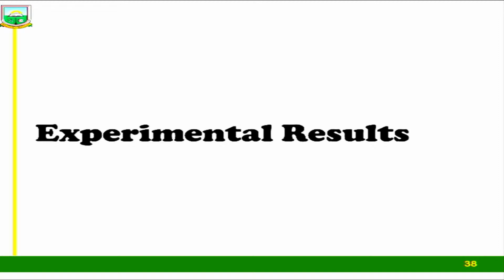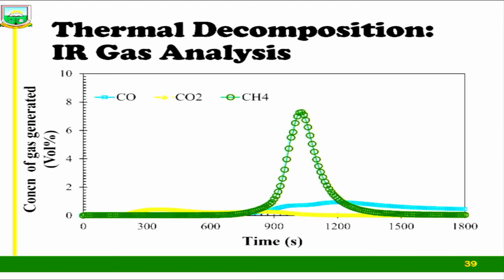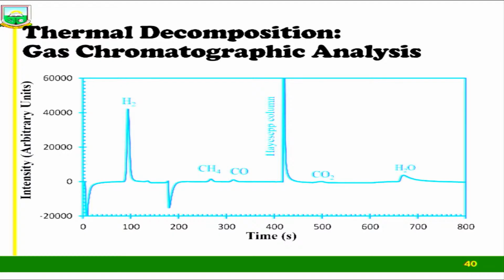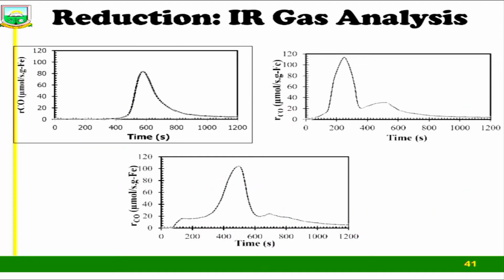Prof. Chair, these are some of the results that we obtained. If you take a look at it, you see that at high temperatures, your polymer, whether it is polystyrene, HDPE, or whatever, will turn into predominantly carbon monoxide, methane, and a little bit of carbon dioxide. We wanted to see whether hydrogen is present, and we used a gas chromatographic analyzer. You can see heaps of hydrogen being produced. These are the gas analysis results for the reduction process.